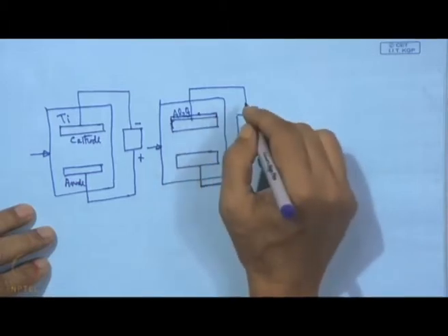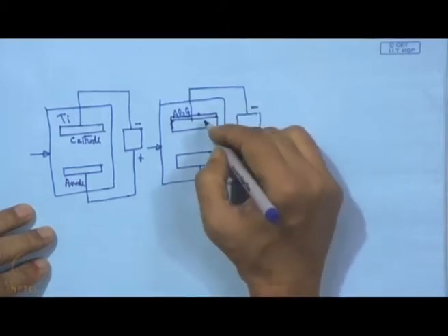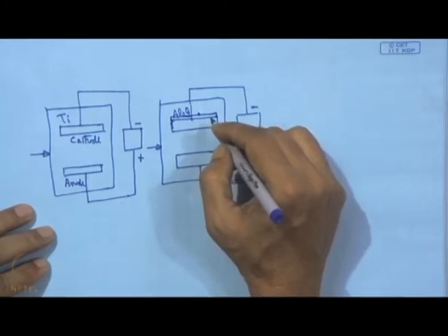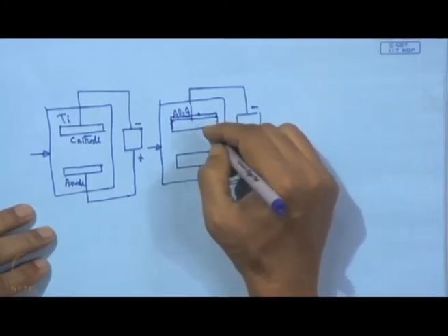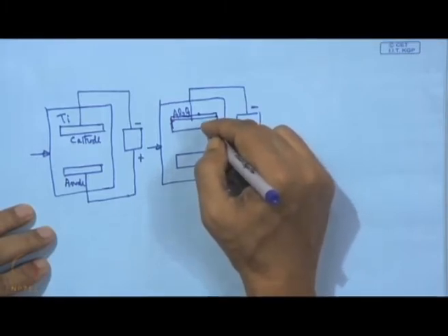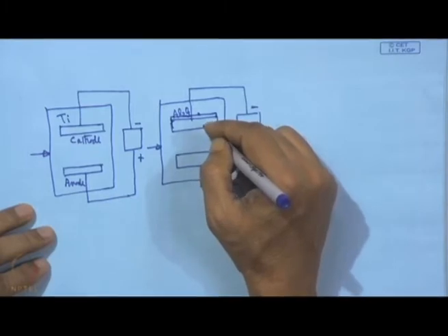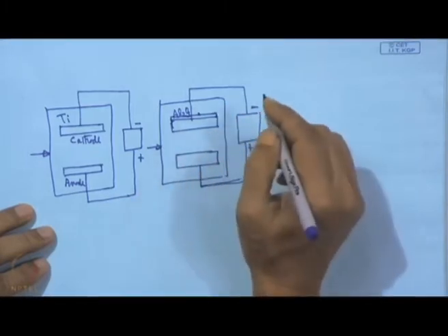So, there will be accumulation of charge and it will ultimately lead to heating of the target, and it can even lead to arc discharge, which is the most undesirable thing in this whole sputtering process.